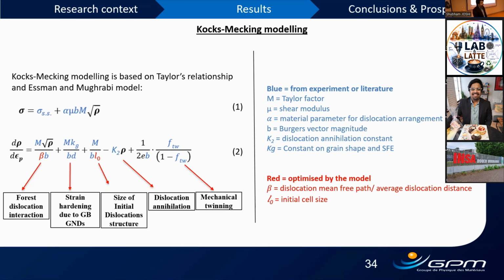Yeah, again, I feel the cooling rate that we calculated was based on Inconel, or a model which was supposed to be working for Inconel. So we tried, first of all, to take that directly in the model and compute. Secondly, this is a very average cooling rate, depending upon the average cell size, but in realistic terms it will certainly not be that average, and we will have a lot of different values. But probably you could clarify. I did not understand.